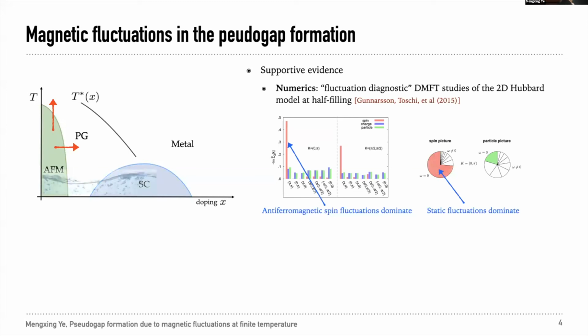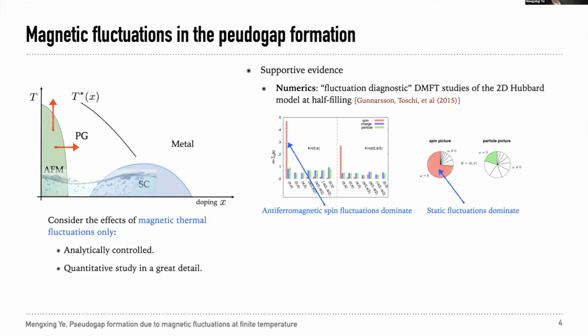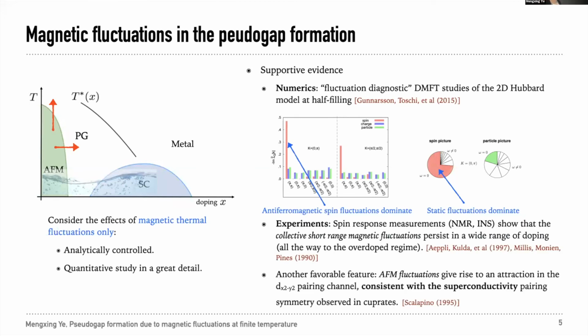I should also mention that I'm not going to talk about anything at zero temperature, and as a result, I will ignore the dynamical fluctuations. It also turns out that if we consider the magnetic fluctuations, just a dynamical fluctuation is not enough to induce any pseudogap. However, if we only consider the static magnetic fluctuations at finite temperature, we can indeed find a way to introduce the pseudogap. Also, it is an analytically controlled calculation, so we can do a quantitative study in great detail. And there is also other evidence for the magnetic fluctuations from well-known experiments going back about two decades.